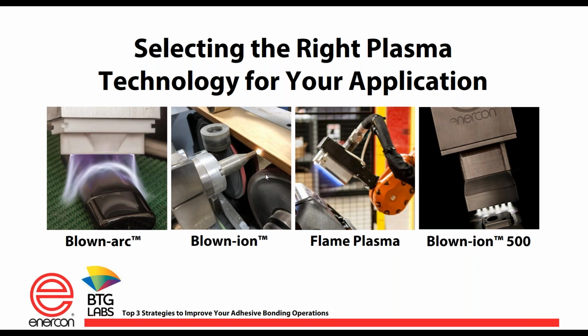Second, there you see the blown ion. That's what most people think of when they think of plasma. It treats about 12 millimeters or about 1/2 inch. Again, it's offered in a single and a dual head version, so we can treat up to about 1 inch wide with one system.